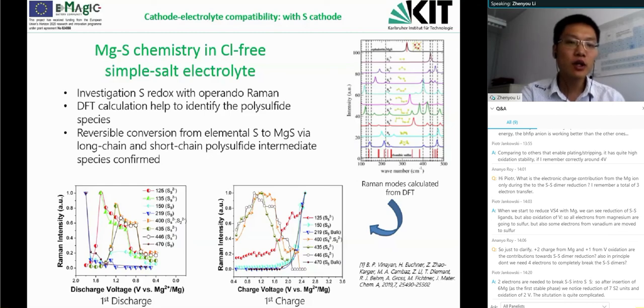And in principle, we have a reversible conversion from elemental sulfur through these long chain and short chain polysulfide intermediate species, and ends up with the magnesium sulfide at lower voltages.